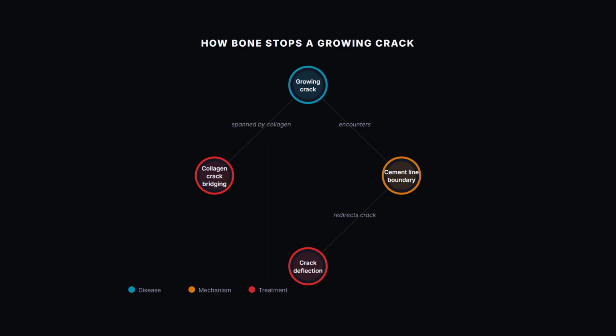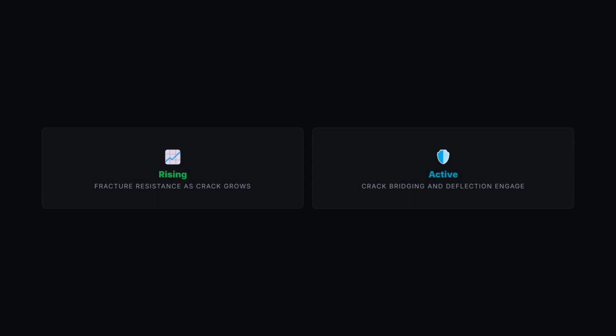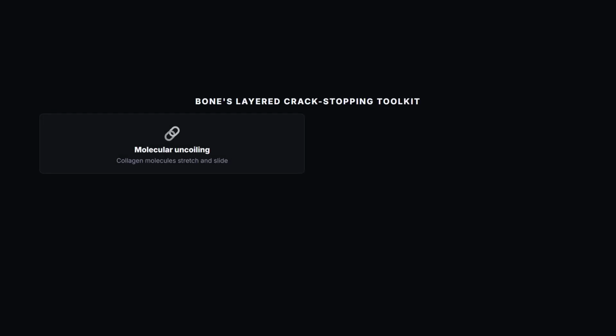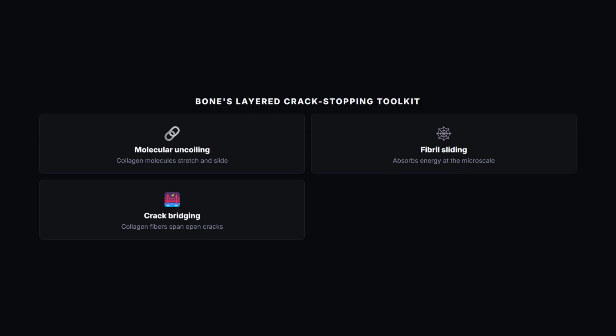These mechanisms measurably work. Fracture toughness testing on human cortical bone shows resistance actually rising as a crack grows longer, called a rising R curve, direct evidence that these crack-stopping mechanisms are actively kicking in and getting more effective as damage accumulates. Altogether, bone stacks up several distinct crack-stopping tricks at different size scales, from molecules sliding past each other, up to whole cracks getting physically redirected. It's this layered defense system that lets bone tolerate constant microscopic damage without falling apart.